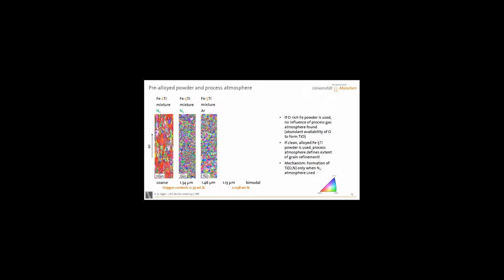Okay. But let's now go back to the 5% titanium, which we know works and where there's no Laves phase, and go back to the very initial question of my presentation. Can we use the process atmosphere to change something in the microstructure? With our initial experiments, I already told you, well, there's a little bit of nitrogen uptake, but it doesn't matter. Why? Because the TiO coming from the dirty powder is what's giving us the grain refinement. This is where the clean powder comes in that we purchased from a different company, and where we have only very little oxygen content in the beginning. And in fact, now we see an effect of the atmosphere.